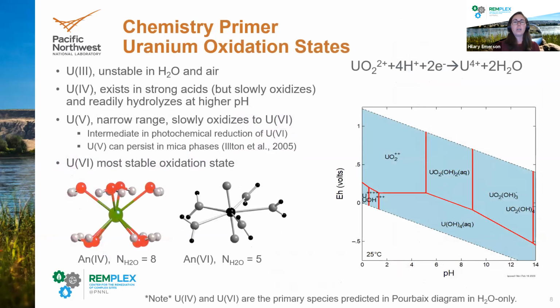Moving along, the oxidation state of uranium is one of the most important factors when we think about how it will behave in the natural environment. Generally, we can have four different oxidation states: +3, +4, +5, and +6. However, the +3 oxidation state is unstable in water and air and is generally only observed in the solid phase. The +5 oxidation state also has a very narrow range of stability in solution and in the solid phase. So the primary oxidation states that we see in the environment are the +4 and the +6 oxidation states.